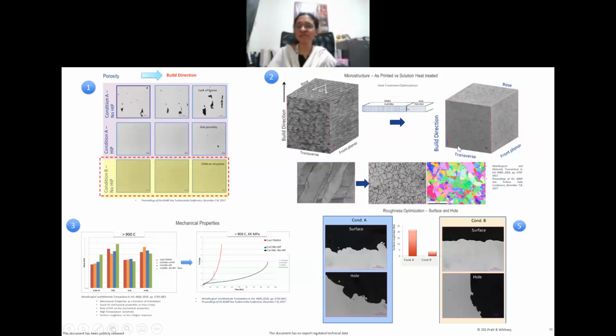So what I'm showing in the second challenge is when we heat treated it, we got a completely recrystallized microstructure. And what we also did in the heat treatment optimization, if you can see this thin line out here, you have the potential to optimize the heat treatment to tailor the mechanical properties to have an advantage or a disadvantage here. So that's what we did. We converted this as-printed structure with little or no defects. Of course, you see some microcracks, you can see some porosity, but which casting or which forging doesn't have it.